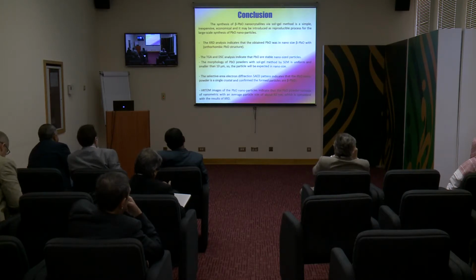The selected area electron diffraction pattern indicates that beta lead oxide nanopowder is a single crystal. High resolution transmission electron microscope image of lead oxide nanoparticles indicates that lead oxide powder consists of nanometric particles with average particle size about 82 nanometer.